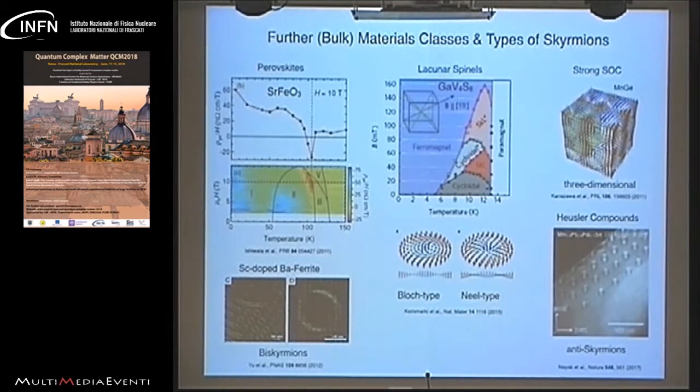There are lacunar spinels which are anisotropic - these were cubic materials that I showed in the beginning - and there are Bloch type and Néel type skyrmions being identified. There are even more complicated textures in manganese germanium, one in this B20 series, there seems to be a three dimensional type of texture formation. Most recently in the Heusler compound something called antiskyrmions has been reported. This generated a lot of interest also in the spintronics community and one of the big questions is where do you find these phases, how are they stabilized - that's the energetics I want to talk about.